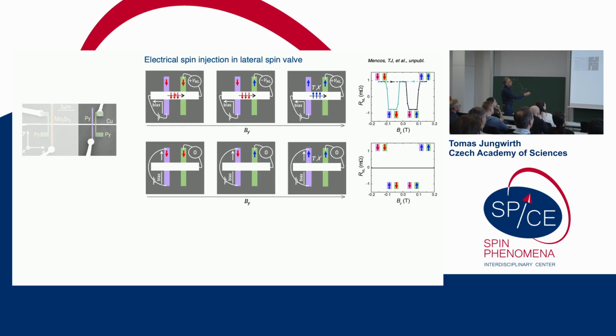So imagine that this is a non-magnetic copper channel, and here is my ferromagnetic injection electrode. You basically push the spin down electrons from the ferromagnet into the channel. Now the electrical current is drained on one side of the device, while towards the other end of the channel, the spins which were injected now diffuse as a pure spin current, no electrical current associated. They diffuse towards the second magnetic electrode where they are detected in the form of this non-local voltage. So this is the setup of the experiment.